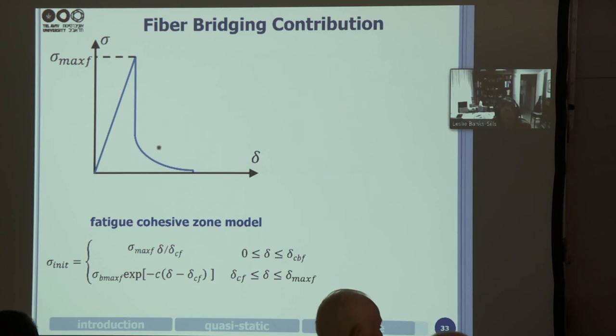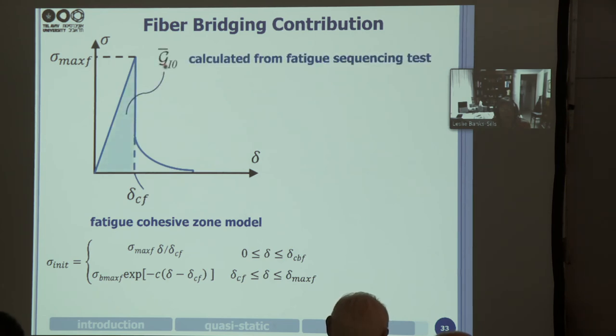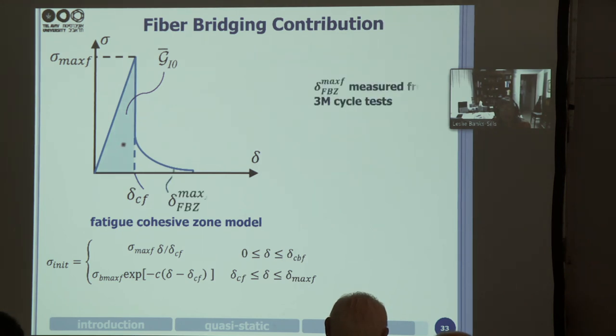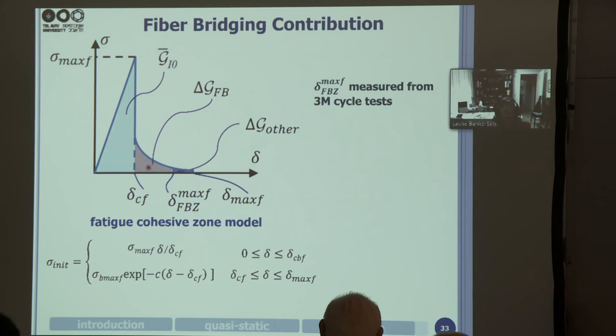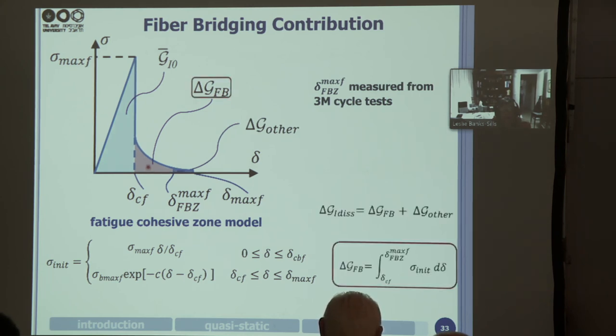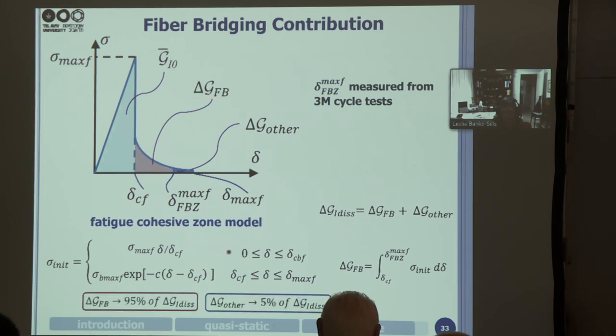Okay, so we have our cohesive zone model, and the area under the curve is G1CF. It's different than what we did previously. And we calculate G10 from the sequencing test, which is the area under this curve. And delta G FB, fiber bridging, is this pink area, and that's what we want to eliminate, and delta G other. So we integrate this curve. Of course, I'm not going into the details of how we got all of the parameters. We get all of the parameters, and we find out that delta G FB, the fiber bridging, is 95% of the dissipative energy. It's much more than in the quasi-static case, and delta G other is 5%.